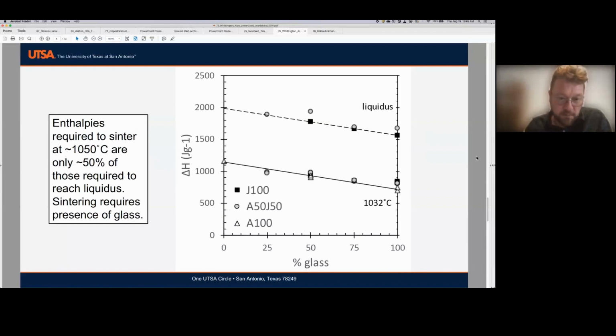This is kind of a summary of our results. So here we have the total enthalpy change required to heat the material from 50 degrees up to its liquidus temperature, for these upper data, and the liquidus temperature there varies depending on what the actual composition of the material is. But we're looking at anywhere between about 1600 and 2000 joules per gram. Whereas to sinter at just over 1000 degrees, we're looking at about half that, somewhere between 700 and 1100 joules per gram. And again, in both cases, the glassier the material on the right, the less total energy is required. Next slide, please.